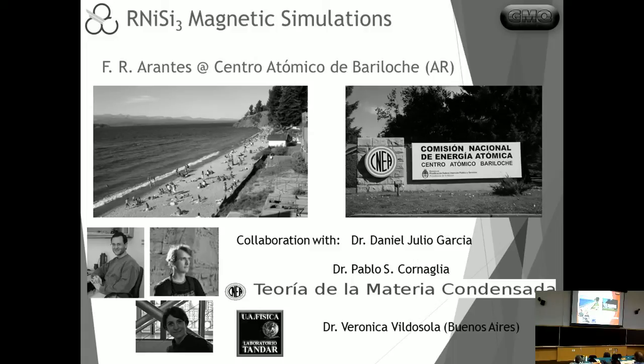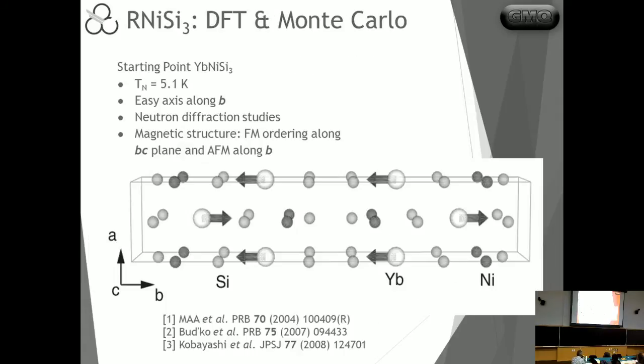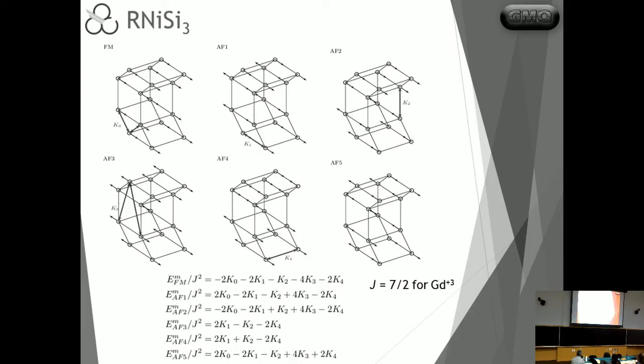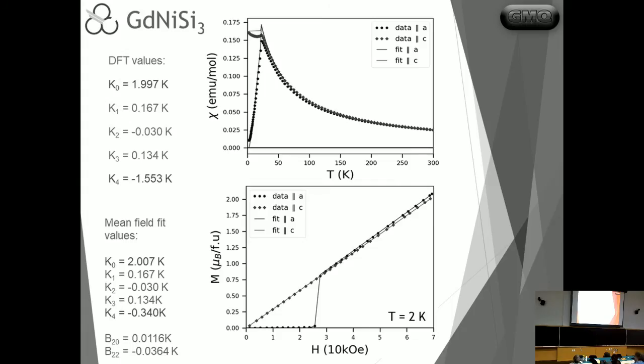Just quickly show this, that we have 2 interesting ones that are almost finished or well on the way. One of them is by making simulations of the rare earth series in collaboration with a group in Bariloche. So Fabiana has been there a couple of times to do these simulations. I won't have time to explain all of the details, but using DFT and Monte Carlo simulations here, they are getting quite successful in some cases already in describing the complete transition of these systems with a complete set of CEF parameters that are self-consistent in all of the measurements that we make.